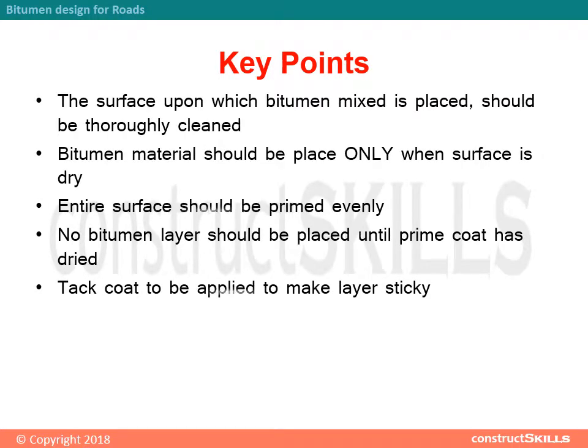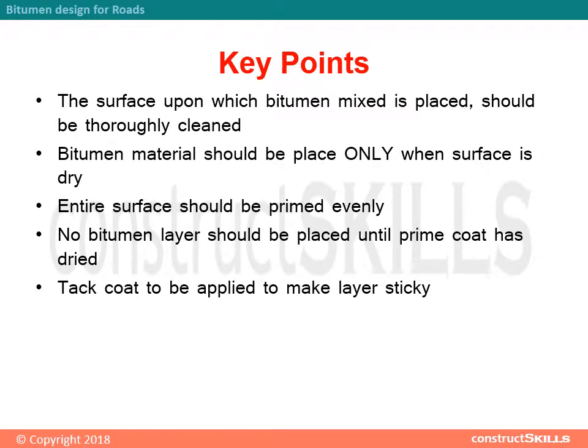Important points to remember before the application of bitumen: 1) the surface upon which the bitumen mix is placed should be thoroughly cleaned; 2) bitumen material should be placed only when the surface is dry; 3) the entire surface should be primed evenly; 4) no bitumen layer should be placed until the prime coat has dried; 5) tack coat to be applied to make the layer sticky.